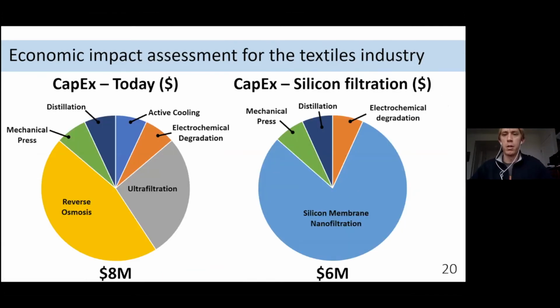And so starting from that point, we can do a lot of techno-economic modeling, and really validating this again with these partners is extremely important. What we come out with in terms of an estimate, and of course a very rough estimate until we can do some on-site piloting, which is hopefully in the cards within the next year, is a CapEx which is relatively similar, but even a little bit less, about 75% of the total for silicon filtration as opposed to the status quo today.